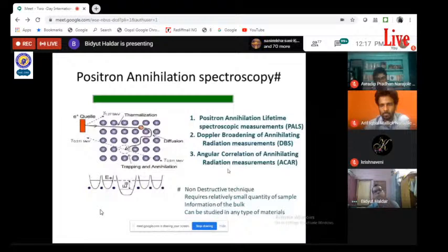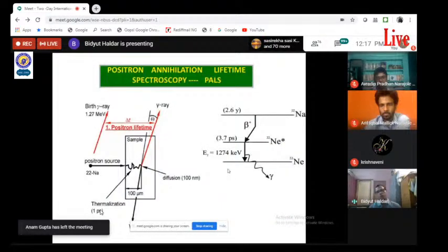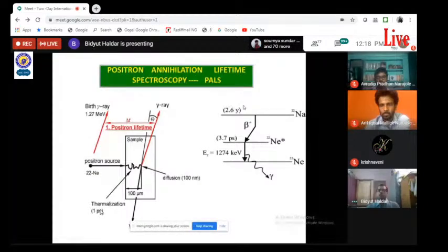In positron annihilation lifetime spectroscopy, we take sodium-22 as our positron source, which emits positrons and has a half-life of 2.6 years. As soon as the positron is emitted, it comes through the excited state of neon, which has a very small lifetime of 3.7 picoseconds. This excited state of neon comes to the ground state of neon by emission of a gamma ray of 1.274 MeV. When this gamma ray is detected, it announces the birth of the positron.